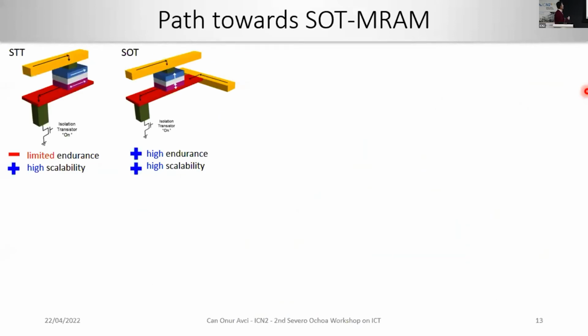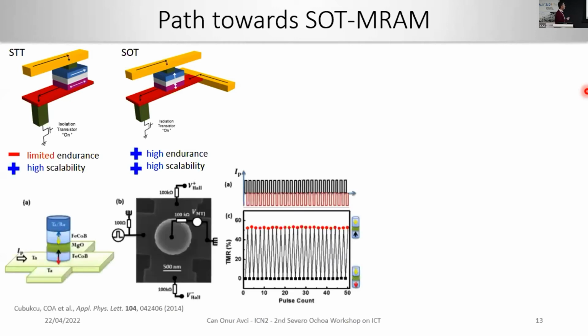Okay, so the early concepts of MRAM were based on spin transfer torque, because of the large current that you need to send through the tunnel barrier. These kinds of devices had somewhat limited endurance, because these tunnel barriers cannot be thicker than a few nanometers. If you send a large amount of current and cycle the device millions of times, then you have a risk of breaking the tunnel barrier. However, spin orbit torques offer an alternative geometry where you can just inject an in-plane current, therefore relieving the stress on the tunnel barrier, and you can also make it with perpendicularly magnetized layers, which is also convenient for scalability.